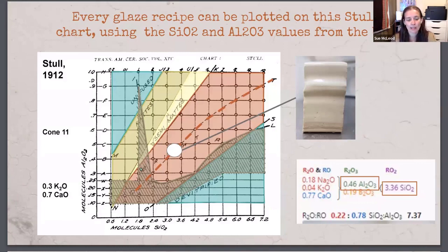And then he created all these recipes, fired them, and then plotted where the matte glazes fell and where the glossy glazes fell, and he found these patterns. So what we've got here is the matte region for Stull. We have to remember that these were Stull's experiments with specific chemistry.